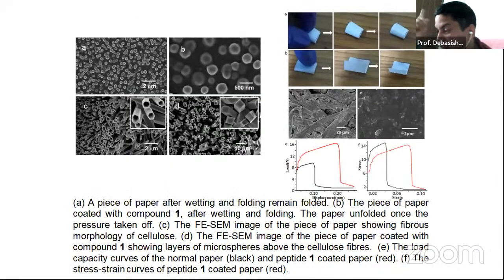But surprisingly, when we study the morphology, what we found is that when it is only the diphenylalanine dipeptide, it forms a nanotube-like structure, and the tubes are perfectly hexagonal. I don't know how they self-assemble in this perfectly hexagonal nanotube-like structure, but they do. That is the reality. That is the experimental data. So what we propose is that they form an antiparallel sheet-like structure by intermolecular hydrogen bonding interaction, and then the sheet folds to form this hexagonal structure. But the general conception is that if a structure folds, that will make a tube-like structure, not this kind of hexagonal structure.